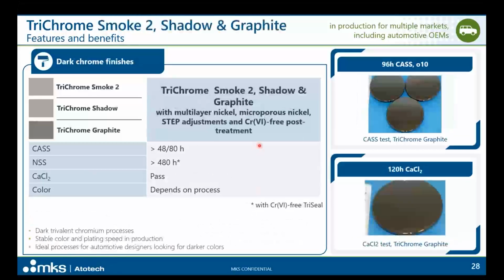If we go to the dark chrome finishes, what we can mention here is that the long-lasting processes with Atotech are the Smoke 2, the Shadow, and the Graphite. Again, based on the same chemistry as Trichrome Plus and giving similar features. That means good CASS, good neutral spray, good calcium chloride results. The color will depend on the different processes.